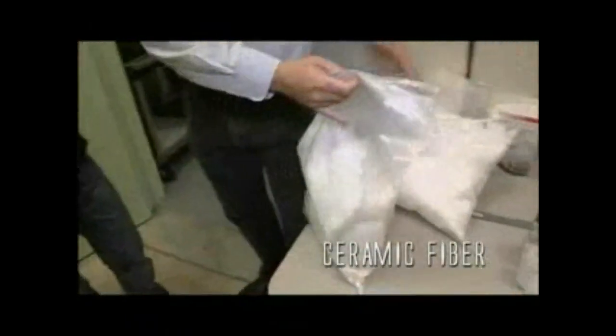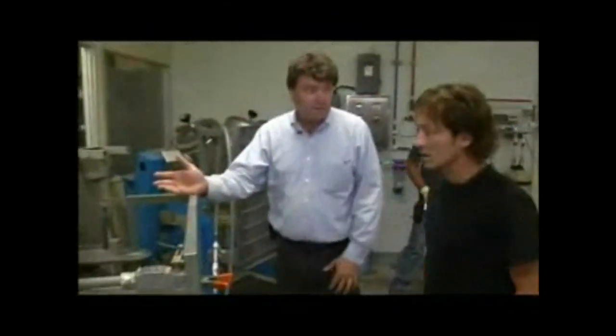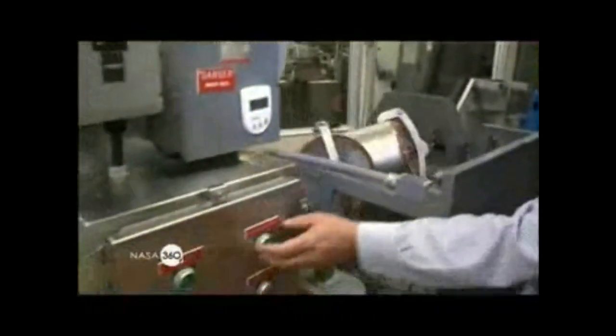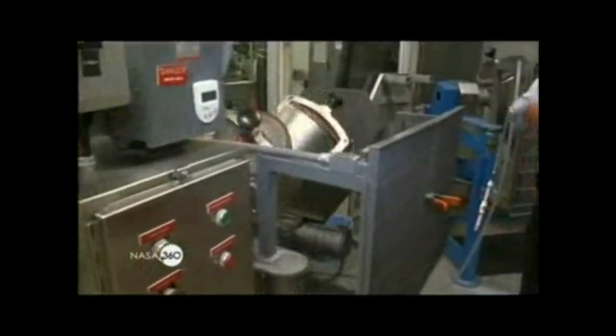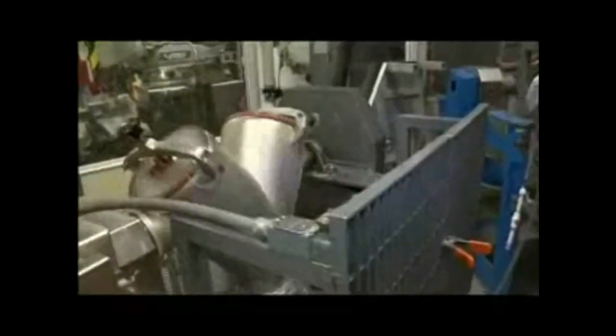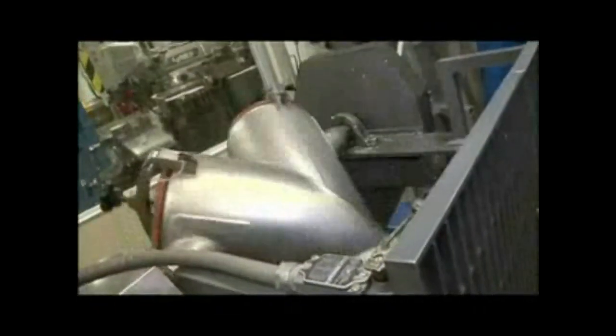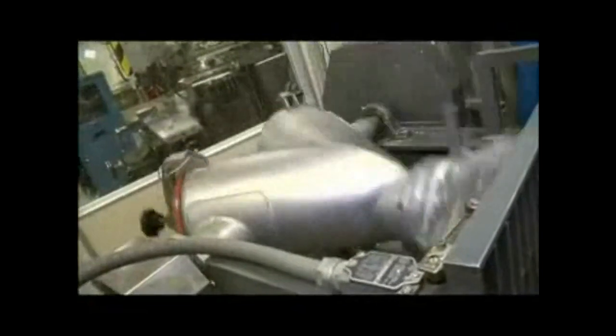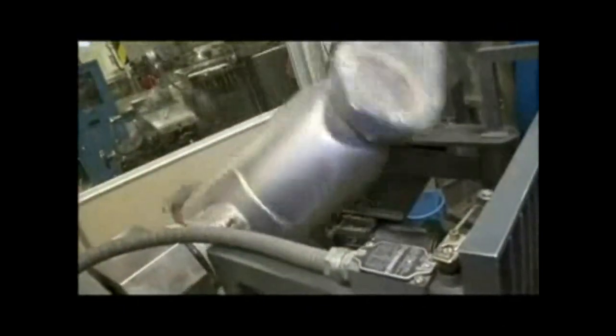Yes. These materials are put into this blender that we have over here with about 25 gallons of water and various chemical additives, ammonium hydroxide, silicon carbide, other surfactants and what have you. We put them in this machine and basically turn it on, and it blends the fiber for around about 12 minutes. Okay. And after the blending process is done, we go ahead and we put it in this casting tower over on the other side of the room.